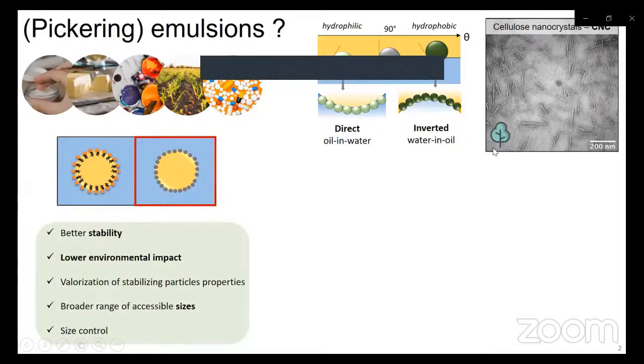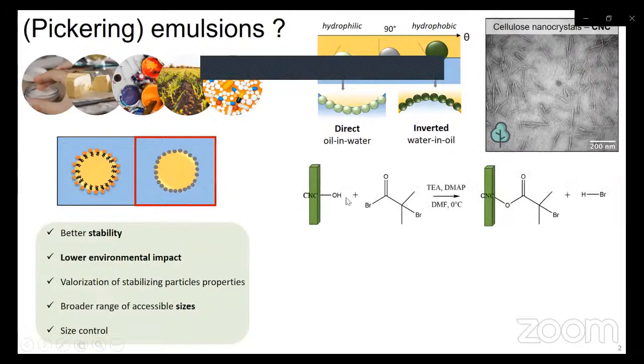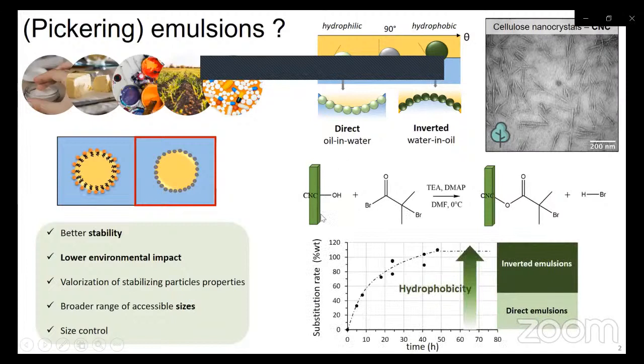They can be extracted from wood, which makes them a renewable resource. But they are mainly hydrophilic by nature because they bear a lot of hydroxyl functions on the surface. To increase the hydrophobicity of these CNC, to allow the stabilization of both direct and inverted emulsions, we chose to use the esterification reaction to substitute the hydroxyl functions by brominated functions. We can follow the substitution rate over time, and as the time increases, the substitution rate increases too, along with the hydrophobicity, which enables us to stabilize both direct or inverted emulsions.